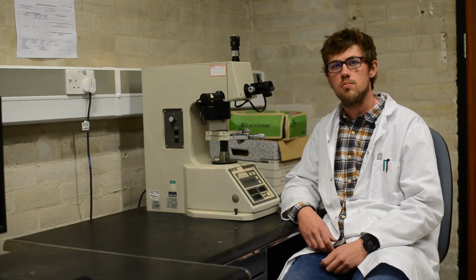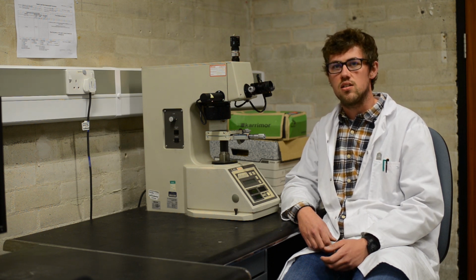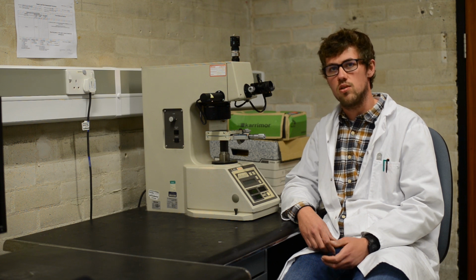As well as the previously mentioned penetration depth stress field, there is also one perpendicular to the indent, where the indents must be spaced at least 2 times the width of the indent to stop interference in the result.